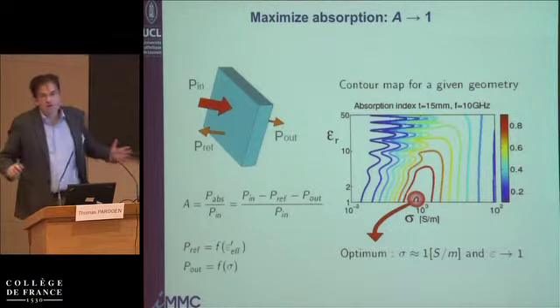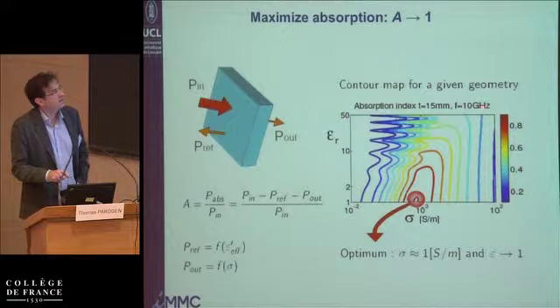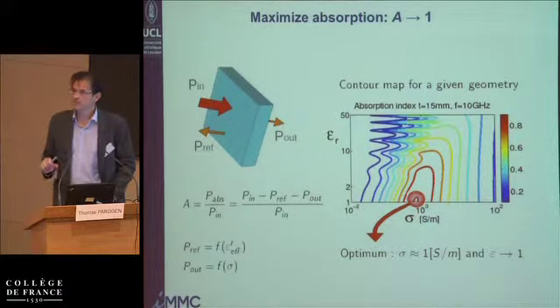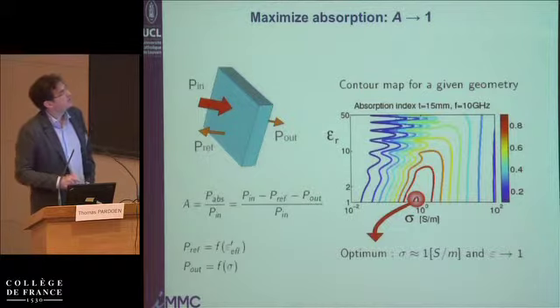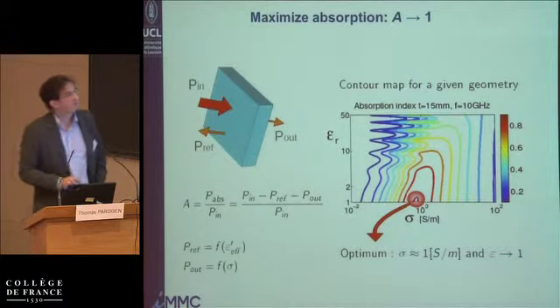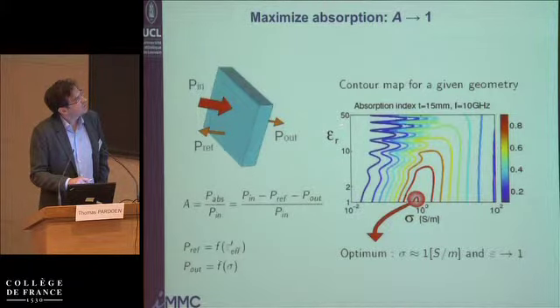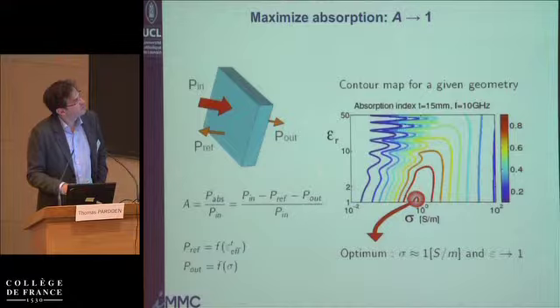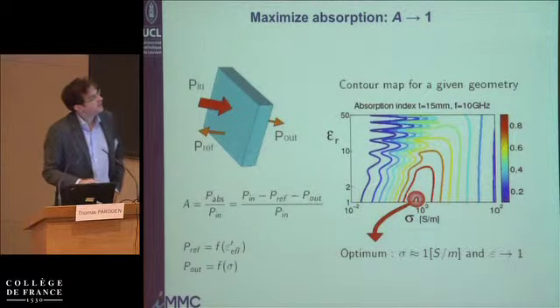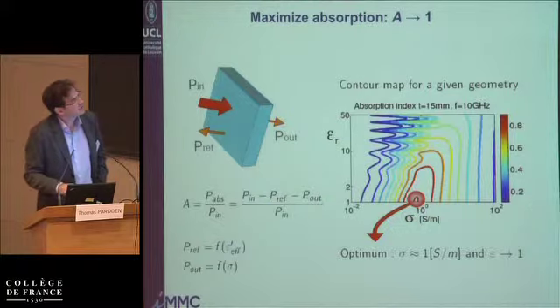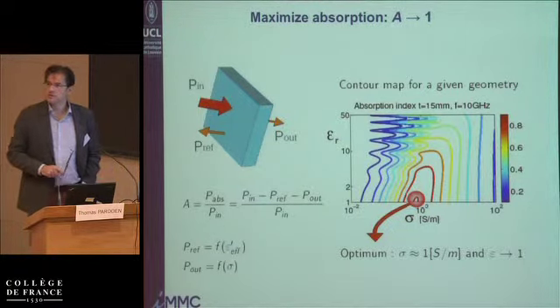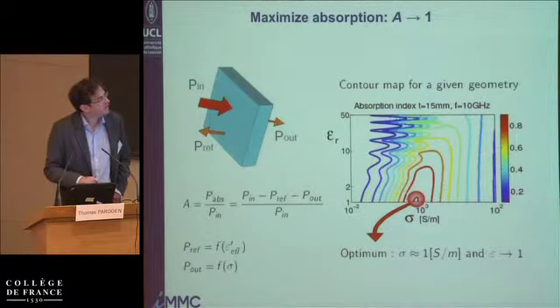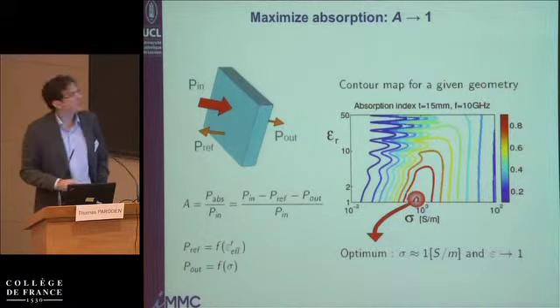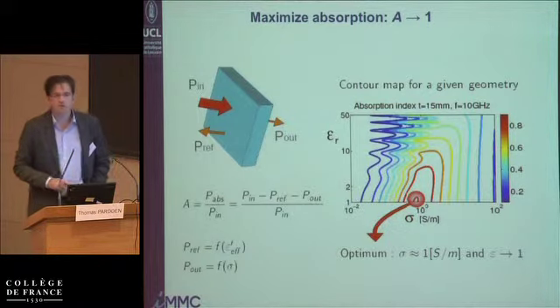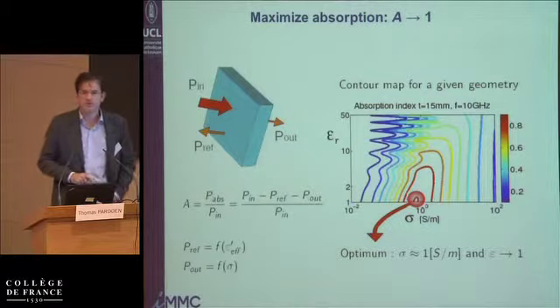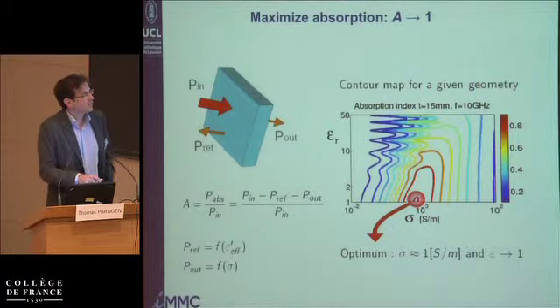So we have to fix the frequency. So let's take 10 gigahertz, and let's fix the thickness of the material. Okay? And then for these two numbers, let's calculate what is the value of the performance index in the dielectric constant electrical conductivity space. And these are isocontours of the performance index, and when it's red, it's the closest to 1. And what you see is that there is a very clear, very narrow region where you can reach high energy absorption. And it's around 1 Siemens per meter, and it's for the lowest possible dielectric constant of 1. This is where you want to go.